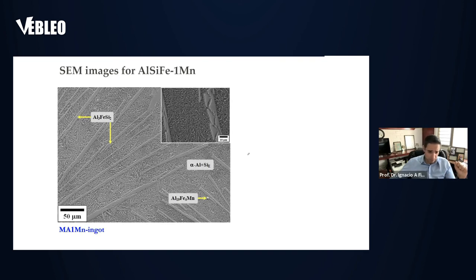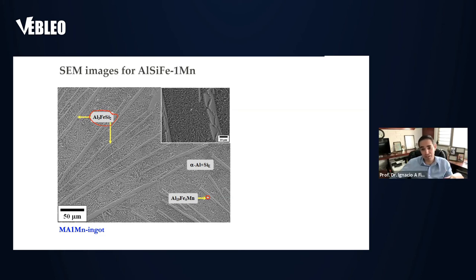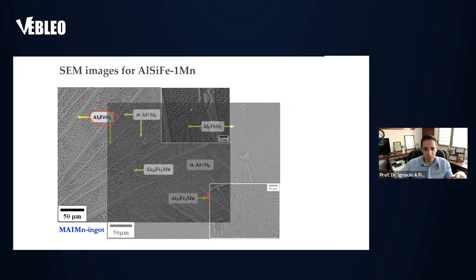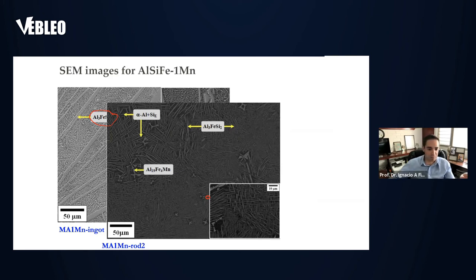I love this image — this is basically textbook quality. Here you can find the eutectic growth: you can see the aluminum phase, which is the bright one, and the eutectic silicon, which is the darker one, surrounded by the intermetallic from the master alloy. With 1% manganese, the intermetallic with manganese starts forming. At high magnification the formation of the eutectic is very clear. Moving to suction casting, the microstructure completely changes: we still got some acicular structure, but more refined and homogeneously distributed.